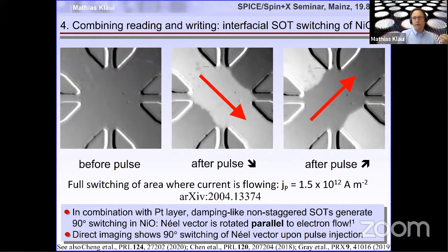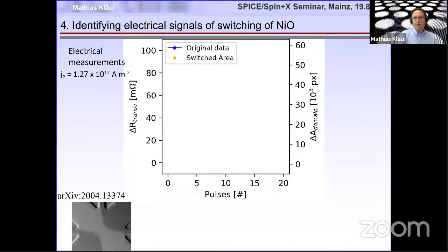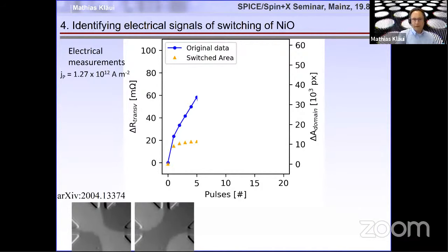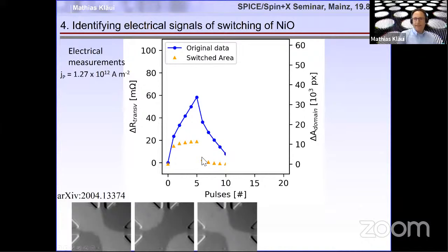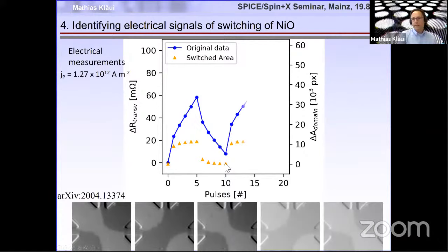But the question is, how much of this magnetic switching is also visible in the electrical signal? For that, we need to do concurrent electrical measurements and magnetic imaging. So we inject current pulses, and we see that indeed we can switch the magnetization. If we look at the switched area determined from imaging, we see after 2-3 pulses this saturates, but the electrical signal continues to go up. Then we reverse the current pulse direction. We see again the electrical signal continuously goes down, whereas the magnetic switching detected by imaging saturates after 2-3 pulses, and again and again.